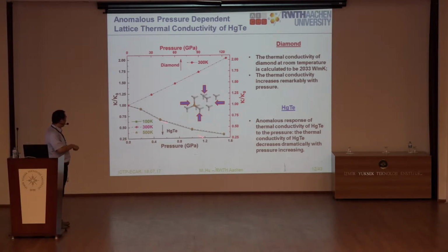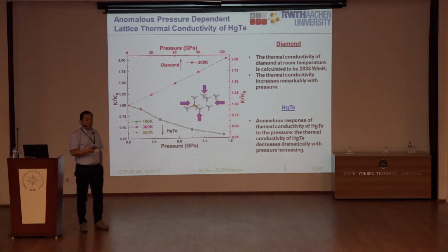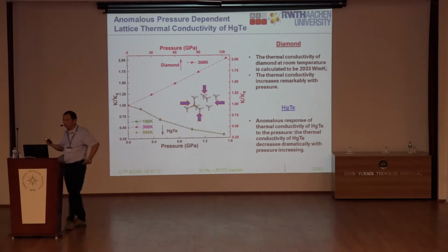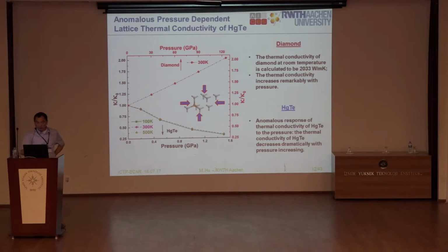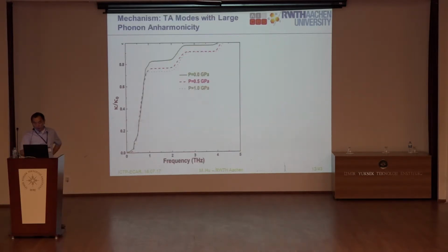This behavior is quite opposite to diamond, as I just mentioned that the normal trend is that thermal conductivity goes up if you apply the pressure, right? So now, why is mercury telluride very special? Actually mercury telluride is also a very good thermoelectric material. Of course, mercury is toxic and not good for the environment, but that's a different thing. Now we have to understand why it's so special.